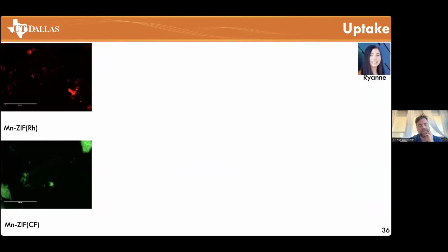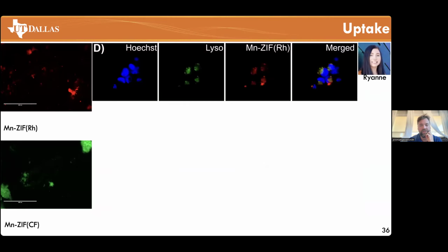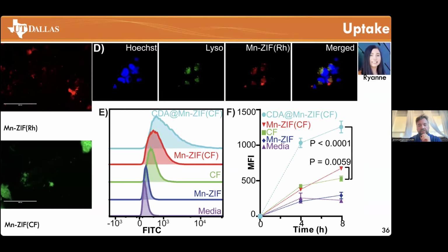Again, we show some uptake experiments, this time with cells. If we put a dye inside of the MOF, we can see where it goes. We can see that we actually don't have particularly great overlap between the LysoTracker and the manganese dye, which suggests that it gets out. The MOF does not just stay in the lysosome, it does degrade and the manganese comes out. So the metals should be able to get into the cell. And then we did cell uptake assays to essentially show that these particles are actually getting into the cell in the first place.